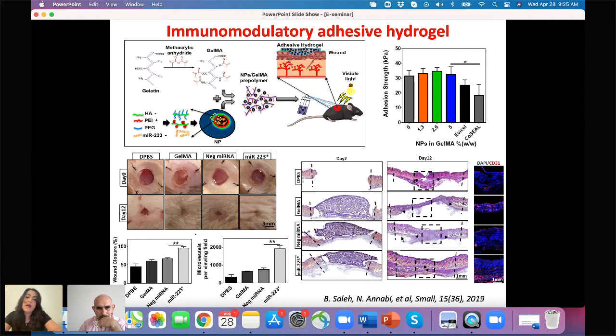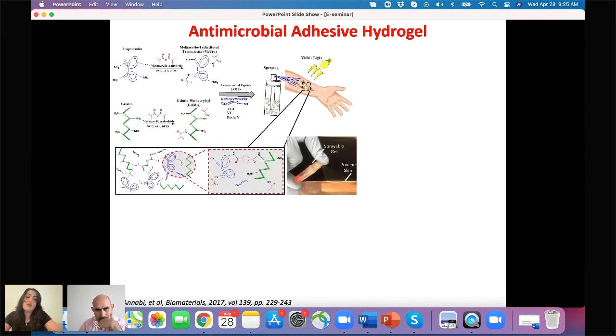But in addition to inflammation, another complication during the wound healing process is infection. So to make these biomaterials antimicrobial, we also work on combining different types of antimicrobial peptides in our hydrogel platform. In this specific project, we used two different extracellular matrix proteins in our skin. One is elastin, and the second is gelatin, a denatured form of collagen. By combining these two polymers, we could form an adhesive hydrogel with mechanical properties and elasticity similar to the native skin. And then by incorporation of an antimicrobial peptide, which can be conjugated to the backbone of the polymer, we can make this material antimicrobial.